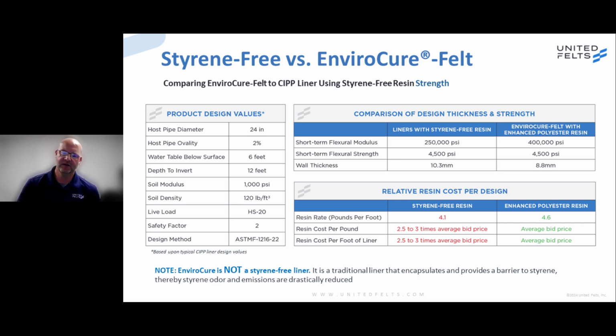Then if you bring that down to the next table, the resin rate required for each of these liners is 4.1 pounds per foot for the styrene-free. It has a little bit lower specific gravity, so your pounds per foot is somewhat lower, compared to 4.6 pounds per foot for the 24 by 8.8 millimeter liner with enhanced resin. The resin cost per pound, the average bid price, is where you're going to fall with the enhanced resin.